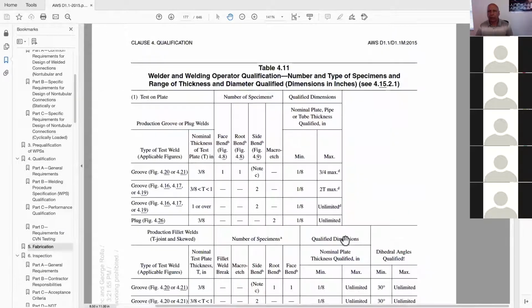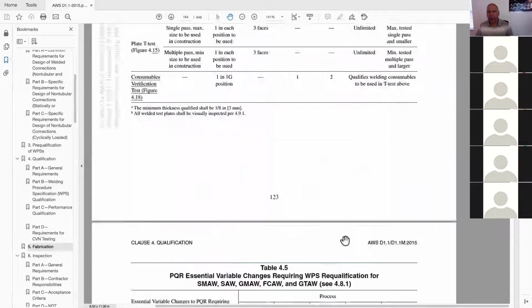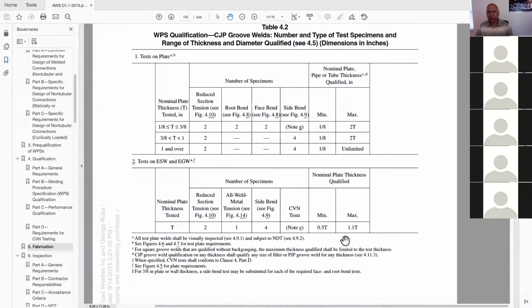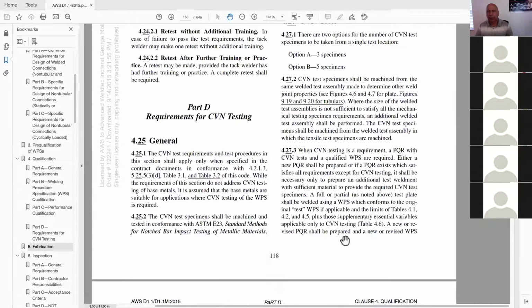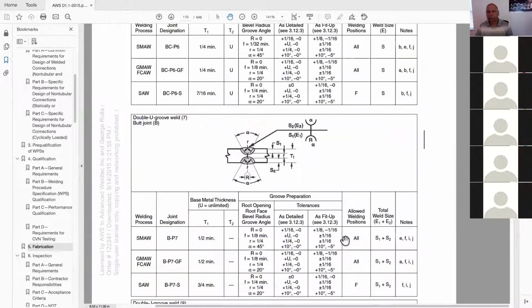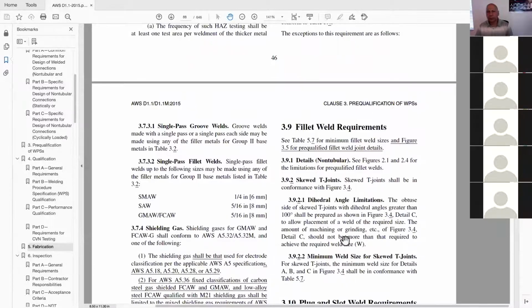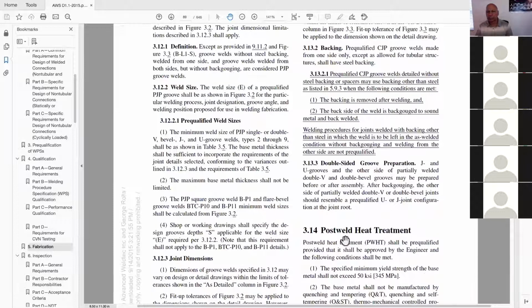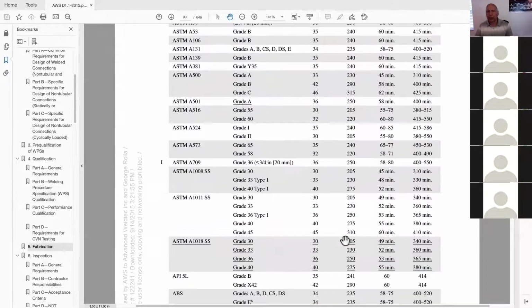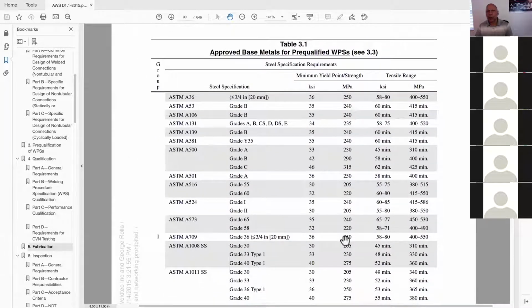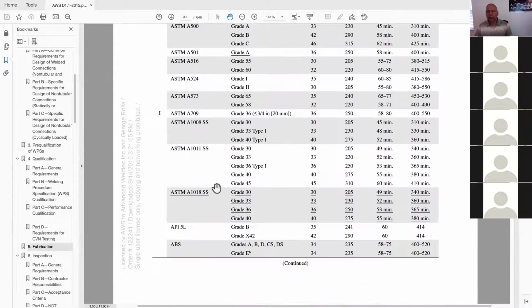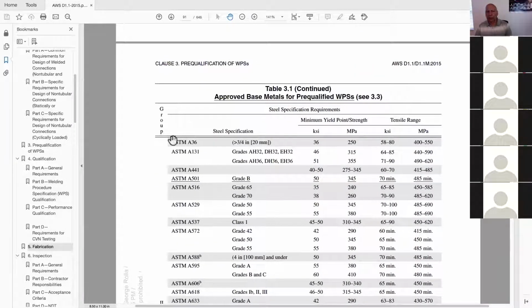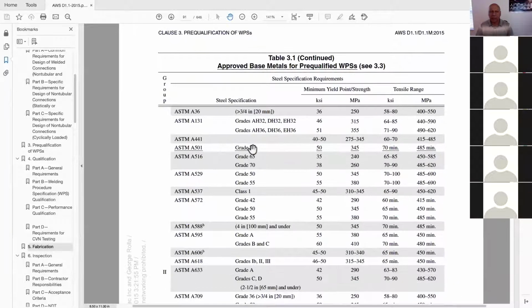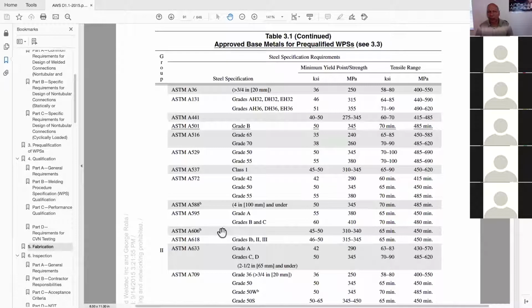For example, if we go back to table 3.1, we would not, it would be absurd to, oops, there we go. So if we go to table 3.1, we want to test the welder on 1-inch plate, so we would use ASTM A36, but it would be thicker than 3/4 inches. Therefore, it would be a group 2 steel. It would have to be welded with a low hydrogen electrode, so that's fine.